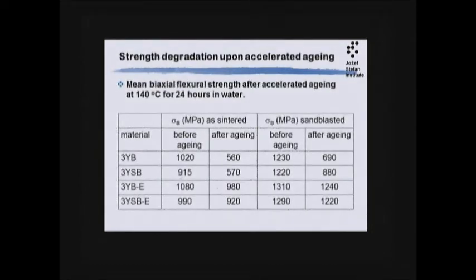Also, with standard grade materials, we observed strength degradation after aging, while the strength degradation in this biomedical grade material was certainly not statistically important.